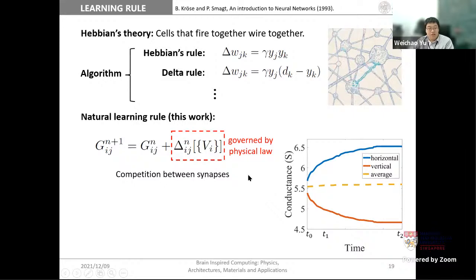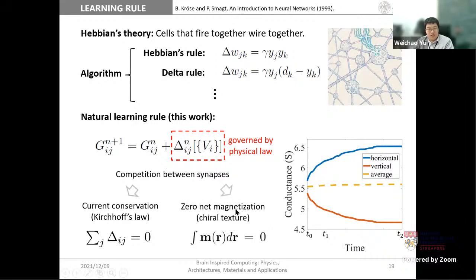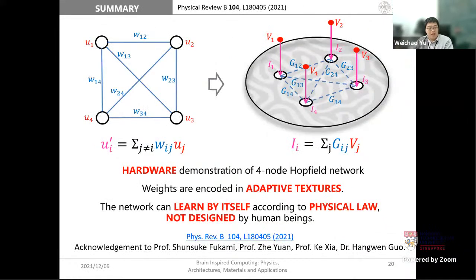The competition between the synapses is provided by, one, the current conservation, which is guaranteed by Kirchhoff's law, and two, the zero net magnetization, which is a property of such chiral textures stabilized by the Dzyaloshinskii-Moriya interaction. And in summary, we demonstrate a hardware version of a 4-node Hopfield network. Weights are encoded in adaptive textures. The network can learn by itself according to physical law, and the learning rule is not designed by human beings.